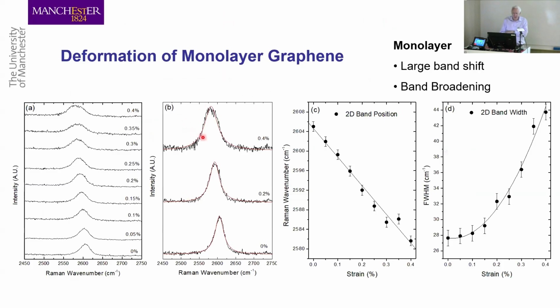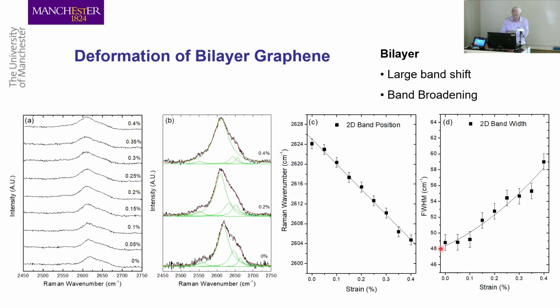If you look at the Raman band, on the same scale, 0 to 0.4%, you can see that this band is actually broadening as you deform it. So the peak position goes down, but the bandwidth actually goes up. The band broadens for monolayer. For bilayer, again, it's a different shape, but it gets broader as you increase the strain. The peak moves downwards and the width goes up.